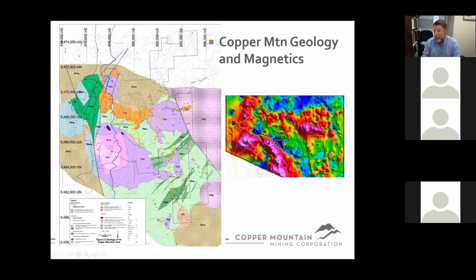This was essentially the core of a fairly large, probably stratovolcano. So you have a pile of mafic volcanics sitting in here, and then you had the Copper Mountain stock and the Boit stock that have intruded into those. Both of these are pre-mineral. The Copper Mountain stock is significant in that it is zoned from diorite on the outside through to monzonite and then into syenite. And syenite's a little bit misleading because this is really just an enormous mass of coarse-grained K-spar in here.